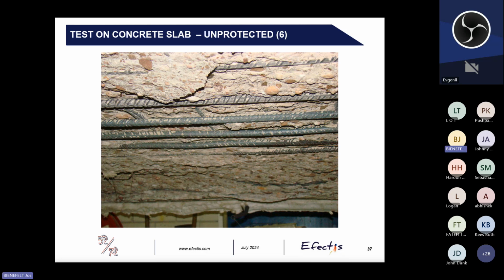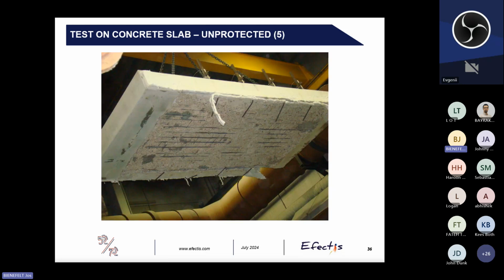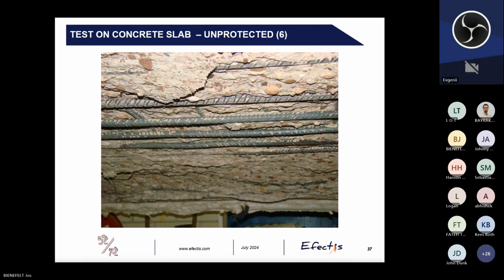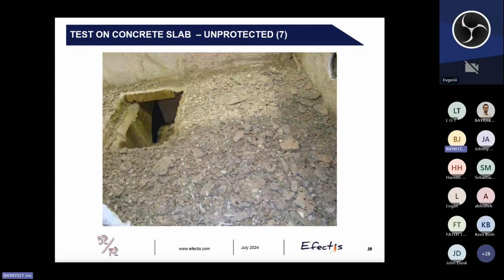So this test really shows that if you have concrete that you test with a high temperature fire curve, as the one you would expect in a tunnel, that spalling might be so severe that your actual structure will be, let's say, eaten up by the fire. So this specimen definitely needed to be protected by a passive fire protection system to mitigate that. And this is a picture from inside the furnace showing how much concrete came off in 25 minutes time.